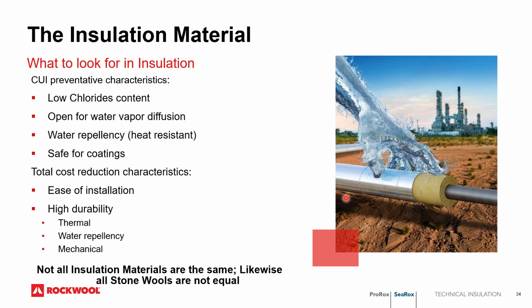I need to verify that for sure, because our tests were simply in the range of the highest situation of corrosion under insulation. So 250 C, which off the top of my head I believe is around 480 degrees Fahrenheit, starts to take us out of the high risk area of corrosion under insulation and brings us into a whole other process situation of high temp insulation. So our inorganic resin does have an upper end limit before heat eventually can cause it to be ineffective. At which point we start to talk about a whole other mitigation process for controlling water ingress and water egress.